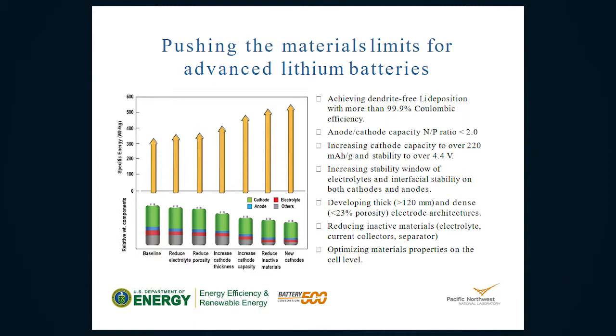just say, hey, I'm going to do this study and get it published in a good journal, you need to do more than that. Then you do analysis on, okay, where we are on lithium-ion batteries, and Wen Zhuan is an expert on this, right? And the best you can get out of a lithium-ion battery is about 300 watt-hour per kg. And then you use the same cell configuration, you replace the anode with the lithium metal. If you just do that, you are still roughly about 300 watt-hour per kg. And then you think about all the cell parameters, what you need to do to get more than that.